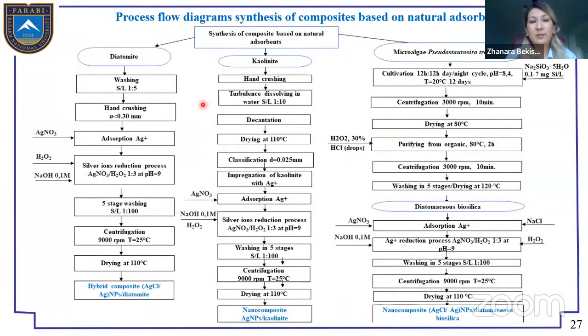And the process flow diagrams of synthesis of composites based on natural adsorbents are presented in the slide. This is the process of obtaining the hybrid composite of silver chloride and metallic silver nanoparticles, with stages of washing, hand crushing, adsorption, and preparing this hybrid composite. And for kaolinite, there is a stage of preparing the nanocomposite with silver nanoparticles based on kaolinite: hand crushing, turbulence, decantation, drying, and classification. After that, obtaining the composite.